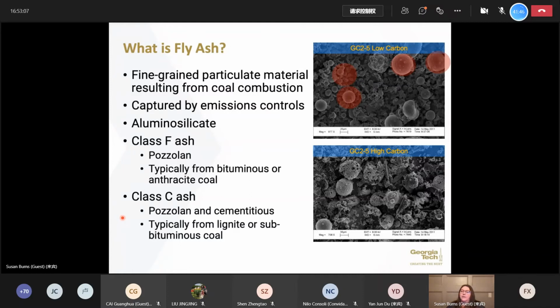concrete. The top image that you see there is a very low carbon fly ash. So it's very ideal for use in cement. When you look at the fly ash in the bottom picture, though, what you're gonna see here are residual organic carbon structures. So these are carbon particles that were not combusted, and that's due to a variety of different reasons, but they're present within the ash, and they are a problem for us because they react with air entraining agents, which are relatively expensive, and they take those up and they cause trouble in terms of the consistency of the product of the concrete. So we don't want to use typically high carbon ash in the concrete industry.